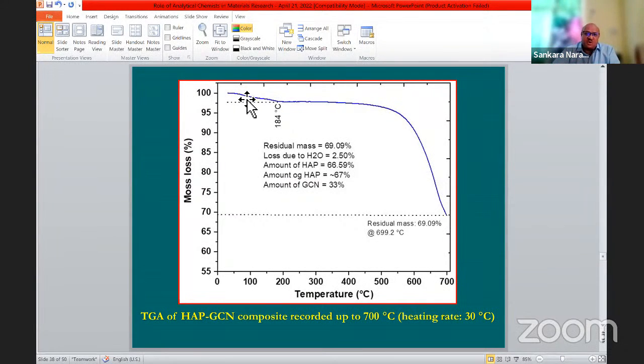Initially there is a small loss of about 2.5% due to removal of moisture, absorbed water and so on. Subsequently, there is a further loss. Based on the residual mass, accounting for the loss of water, we calculated the amount of HAP as 66.59%, approximately 67%. If the HAP is 67%, we can indirectly calculate that the amount of GCN is 33%.